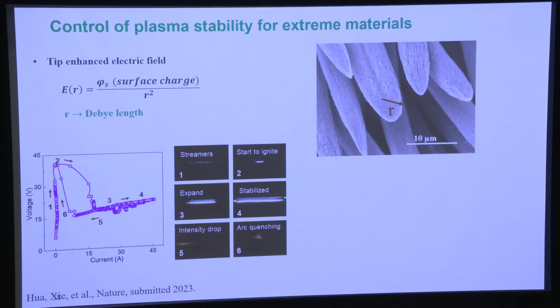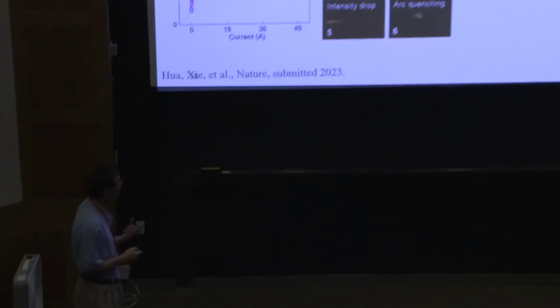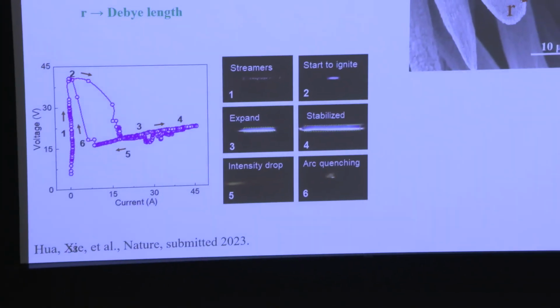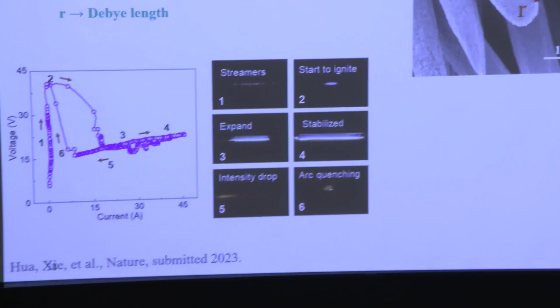This plasma is very uniform and stabilized between the two electrodes. And if you reduce the current, even when the voltage is about 15 volts, the plasma is still stabilized there, very uniform. What does it mean? It means that we created a new plasma that can be uniform with a larger volume. And what can it do? Well, it can do this.